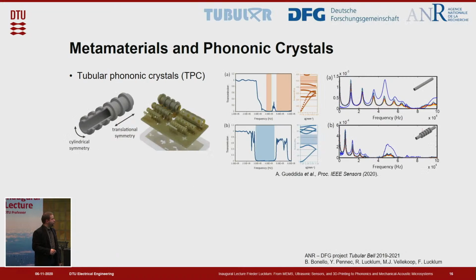But we don't have to stop with 3D structures, with normal Cartesian arrangements. We can also look, for example, at these tubular structures, or we have actually looked at these tubular structures, where instead of having 3 translational symmetries, we now have 1 translational symmetry along the length of the tube and 1 cylindrical symmetry along the circumference of the tube. Again, 3D printing allows us to realize that behavior, whereas in traditional machining or traditional fabrication, realizing this tube structure would be quite difficult.